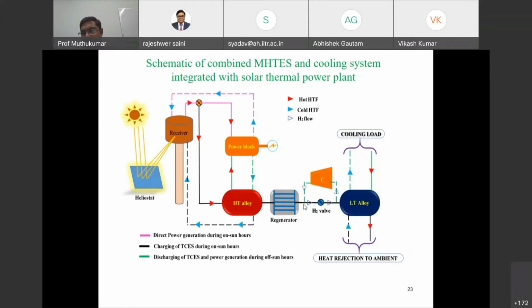Then after compression, during the reverse cycle, I mean the discharging cycle, you pass the pressurized hydrogen at about 25 bar through the regenerator, so it will get somewhat heated up. Then you supply it to the high temperature alloy. Now what is happening in the high temperature alloy? You are supplying hydrogen at high pressure, about 25 bar. The corresponding equilibrium temperature of the high temperature alloy at about 25 bar will be around 450 degrees Celsius. Okay, so that means you will be getting heat output at 450 degrees Celsius. Now what is happening in the system?